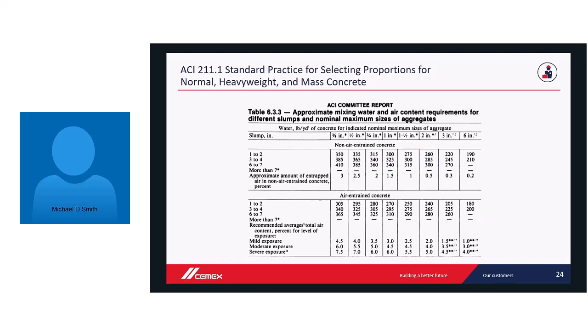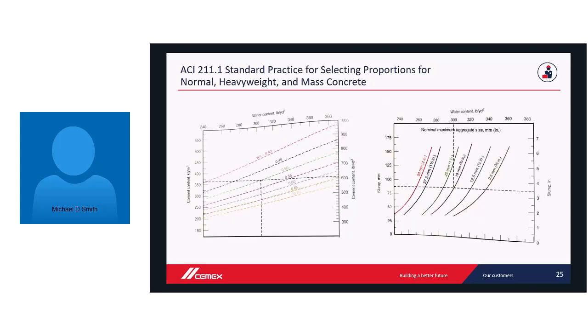Once you determine this, you can calculate your cement content from your water content and your water cement ratio in the next slide. So there are some general rules of thumb here for certain water cement ratios. If 325 was our water content and we needed a 0.50 water cement ratio, then it'll tell us generally how many pounds of cement we're targeting. And then on the right here, it gives you some general information about the aggregate size that you use. Larger aggregate sizes have less surface area, so they don't require as much water to coat them. On the other end of the spectrum, the 1/2-inch and 3/8 mixes have a lot of surface area, a lot of particles in that aggregate, so they need a little bit more water to get the same fluidity. So this is a chart based off water content for the slump that you're trying to target. It's going to shift depending on what your maximum size of aggregate is in the mix. So it provides you with some general rules that you can go by to design your mix from scratch.